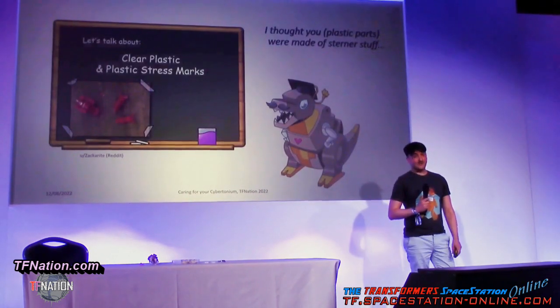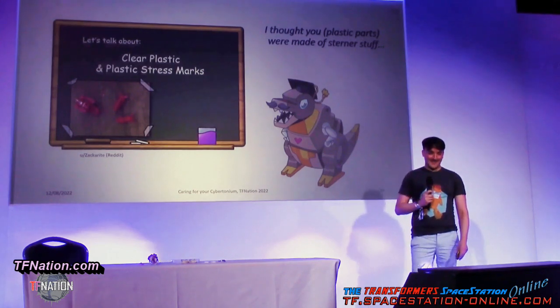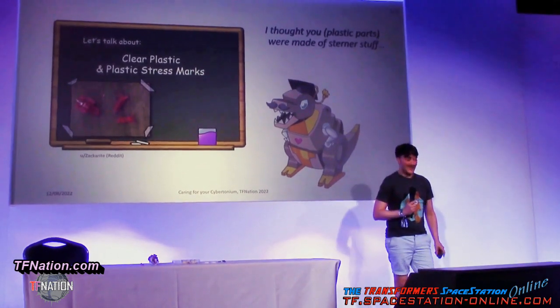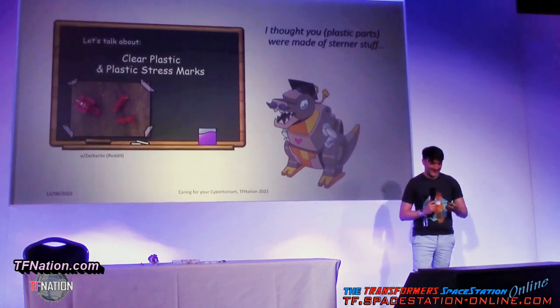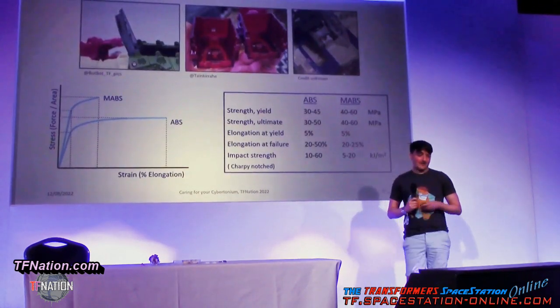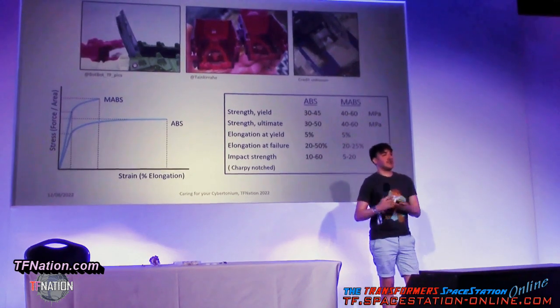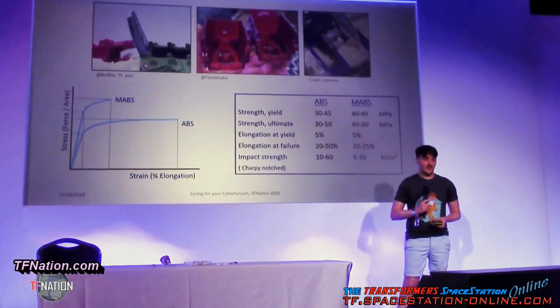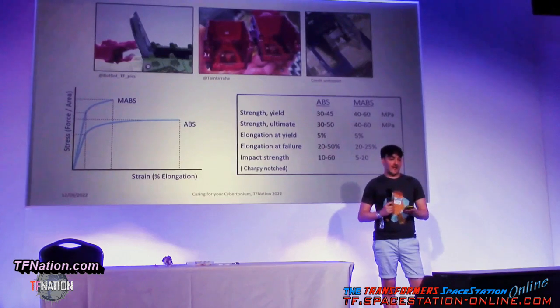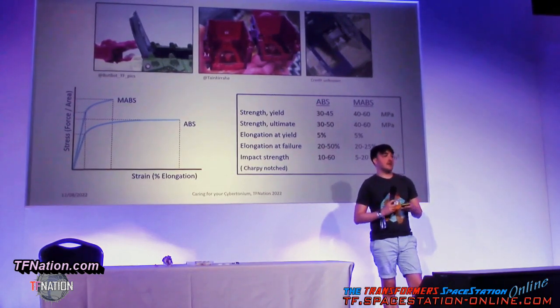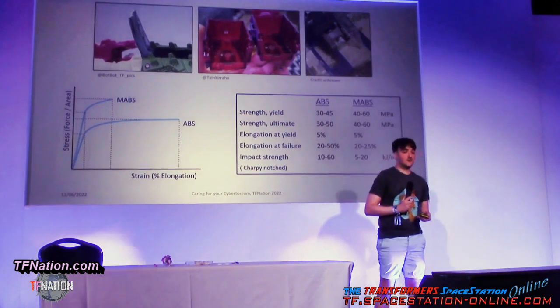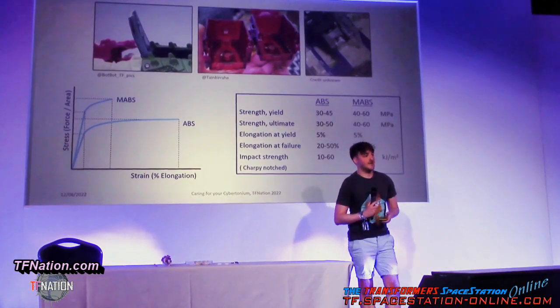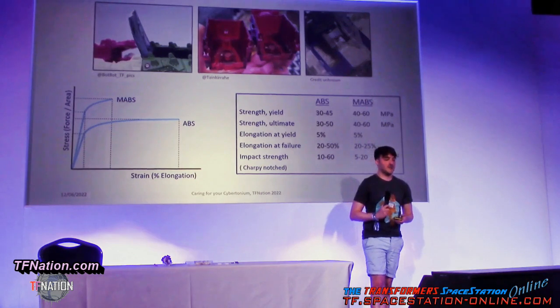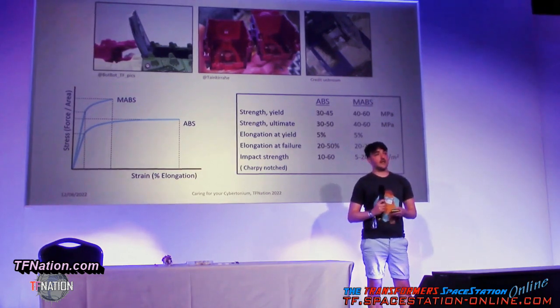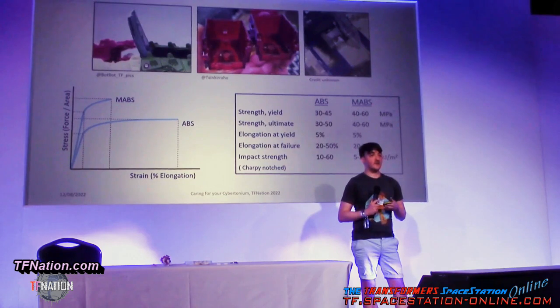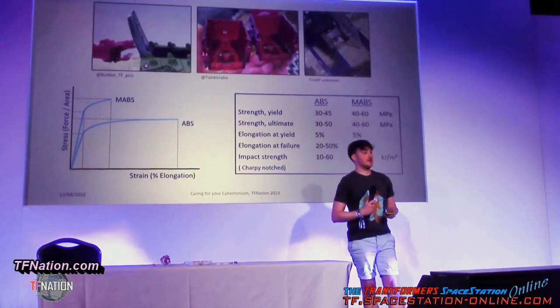So, now we've got some basics down. Clear plastic and stress marks. In fact, I've got a very good example sitting on the table afterwards. I've mentioned already about the different natures, the crystalline nature versus the amorphous nature. What I've done here is look at some of the recorded material properties for both ABS and MABS. So very similar chemical structures, but we can see that they can take quite different amounts of strain, energy, elongation, and stress.